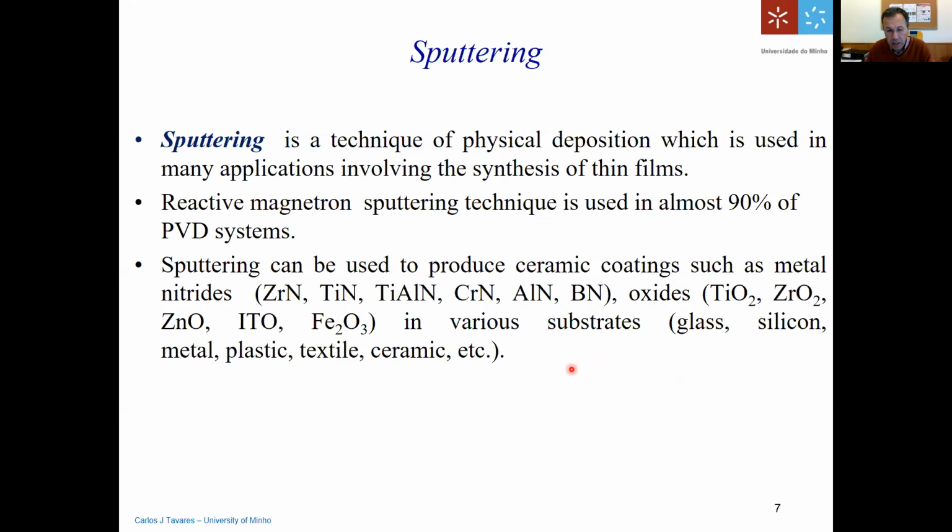And in some applications, you can also do amorphous carbon coatings, for example, for some specific components of motors where there is a lot of wear. For example, in the pistons of the motor in a car, there are certain parts where the friction coefficient has to be very, very low, so you will not have a lot of wear and will not damage the piston.